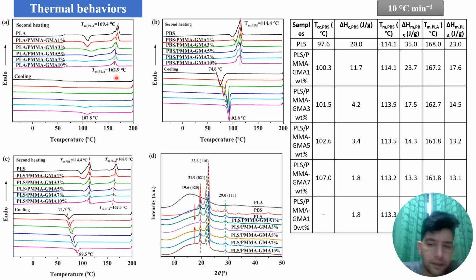In a polymer blend, if the melting temperature decreases, it means that the polymers like each other and have miscibility with each other. So we can say here the miscibility increases. Another point is the second melting temperature, which is small and also disappears, which also shows improved crystallization. In the cooling, because of the amorphous nature, there is no Tc, while by adding the compatibilizer a small Tc is observed at 107.8, which is the evidence that it helped to improve nucleation and crystallization. So from this data we can say that the crystallization of PLA is improved.